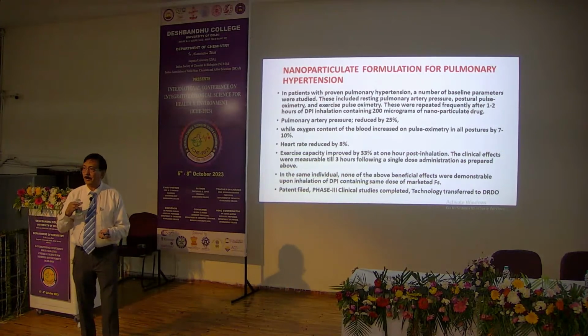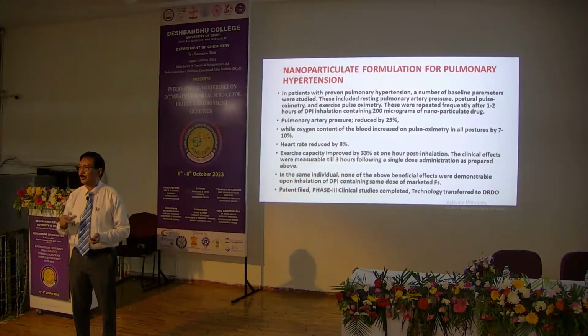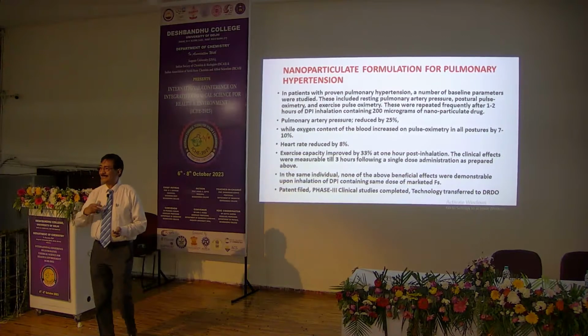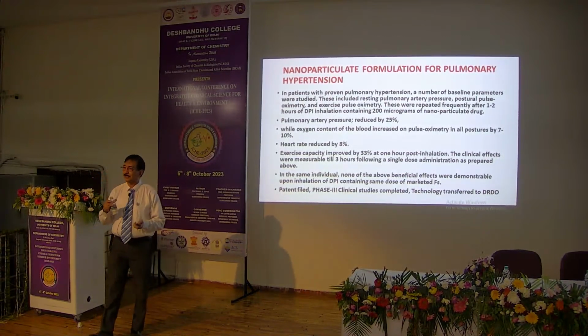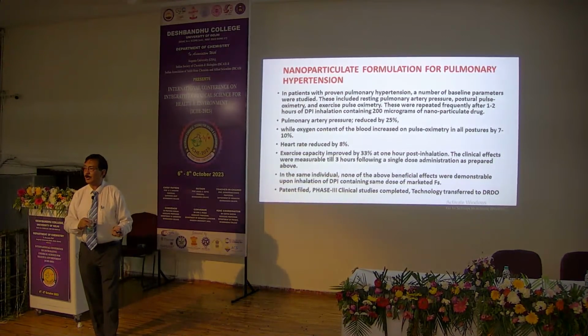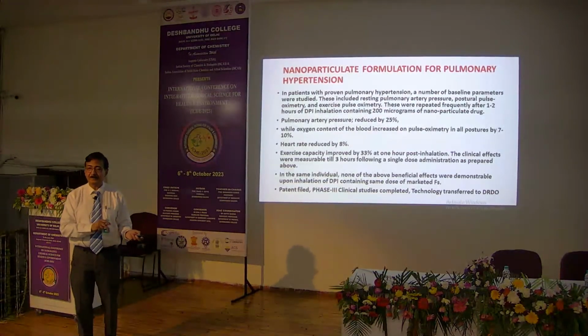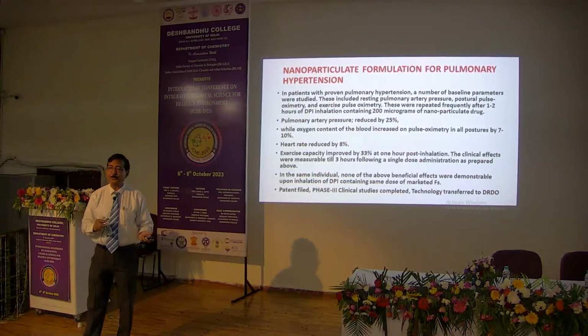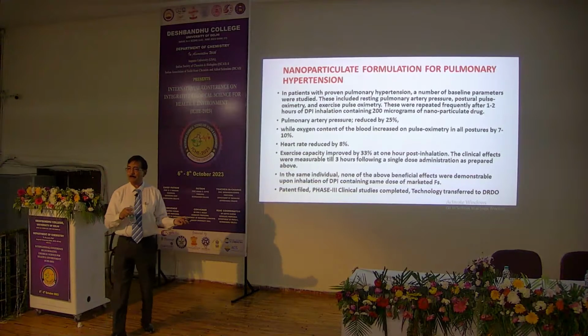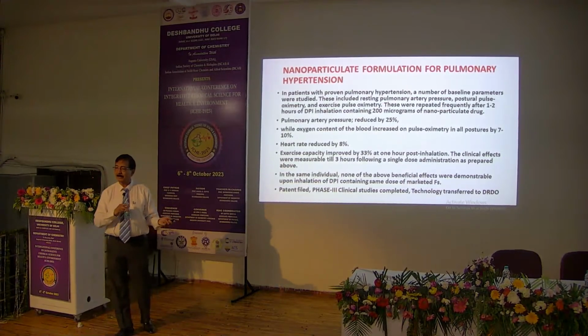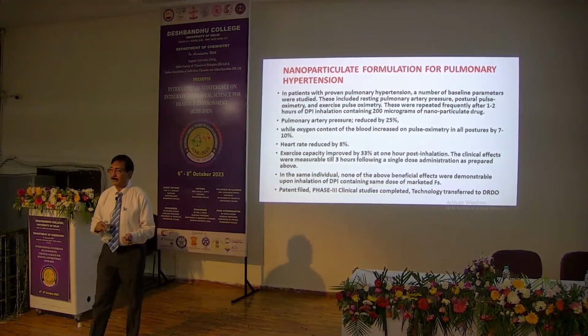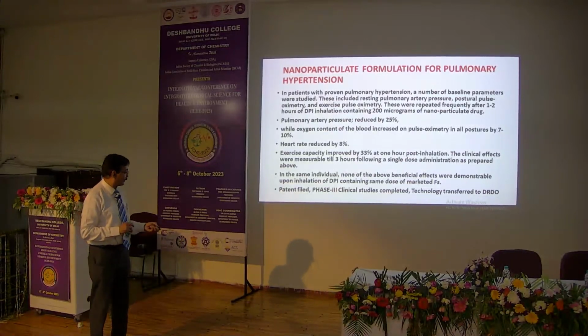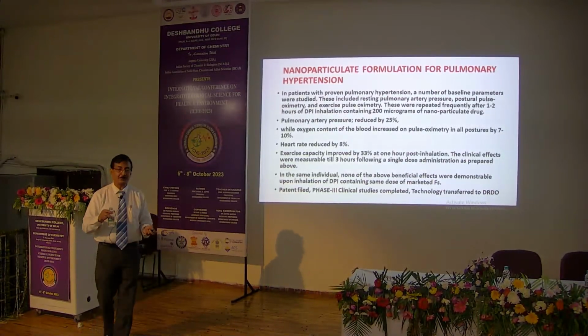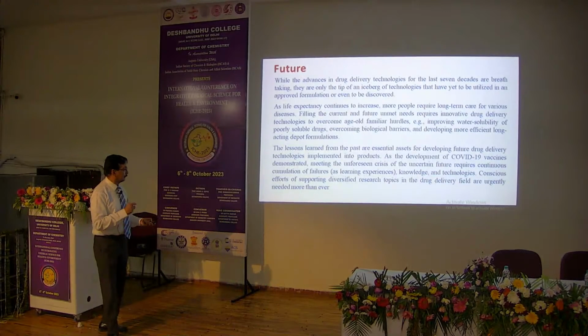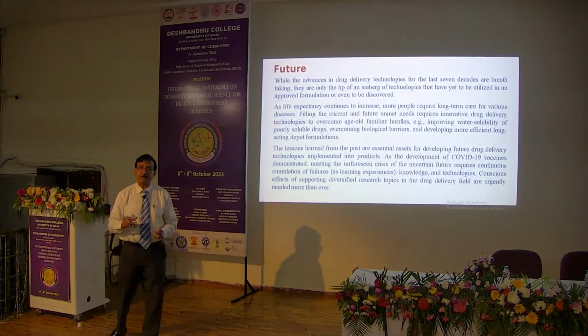They will get a golden time of about 6 to 8 hours, and their oxygen content and exercise capacity are increasing, so they can easily be brought back to the hospital at the base location and be treated. We have gone through phase 1, phase 2, and phase 3 clinical trials. It is already adopted by defense personnel. So this is one success story which I want to share with the students. And the future is very promising.